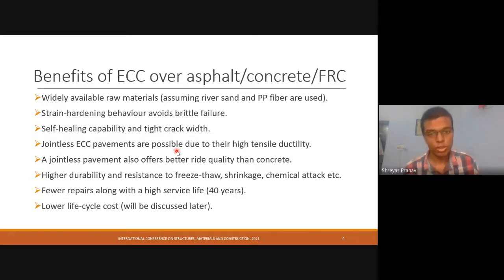And secondly, the most important aspect is that ECC, as I had already mentioned previously, exhibits strain hardening behavior, or in other words, tensile ductility, and that helps in avoiding the brittle failures, which is very common in concrete. So in concrete, you just typically have one large crack, and suddenly the specimen fails. But that is not the case in ECC. Also, because of this high tensile ductility, there is the possibility of making jointless ECC pavements, because the stresses are automatically neutralized because of this tensile ductility.